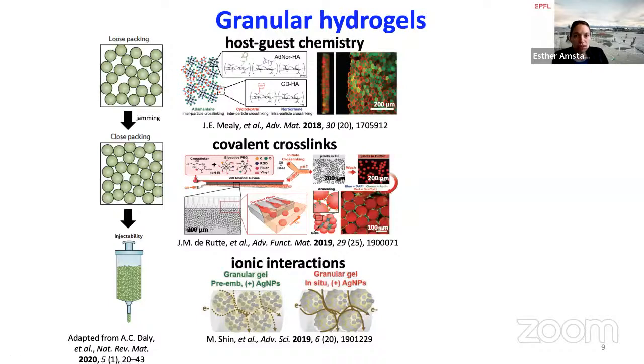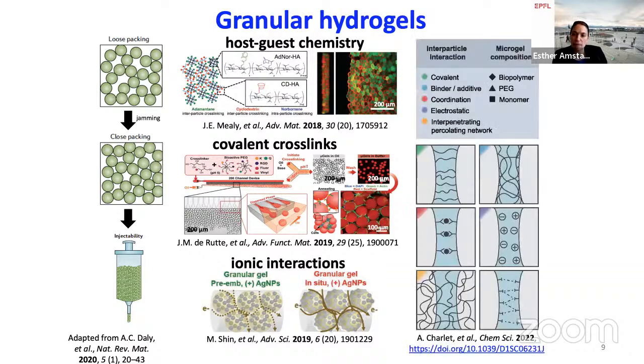But if you go through this literature and analyze how these connections actually influence the stiffness and toughness of this granular material, at least I was very surprised because, well, maybe these connections help to increase the stiffness by a factor of 1.5 or so, but not by more. So all of these materials are still very weak, such that you cannot really use them for any load-bearing application.